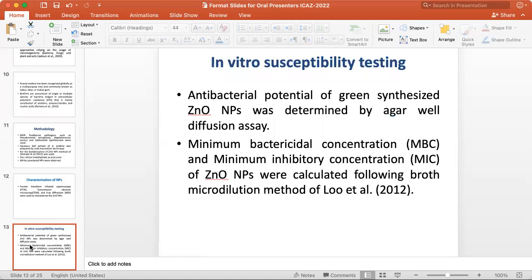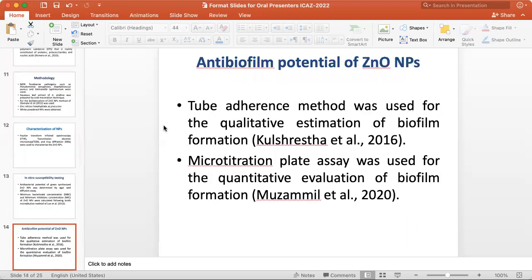Later on, in vitro susceptibility testing was performed by using two different methods. One was the broth microdilution method, through which we determined the minimum inhibitory and minimum bactericidal concentration of the nanoparticles, whereas the agar-well diffusion method was employed to check the antibacterial potential by using different concentrations of zinc oxide nanoparticles, and the diameter of the zone of inhibition confirmed their antibacterial activity.